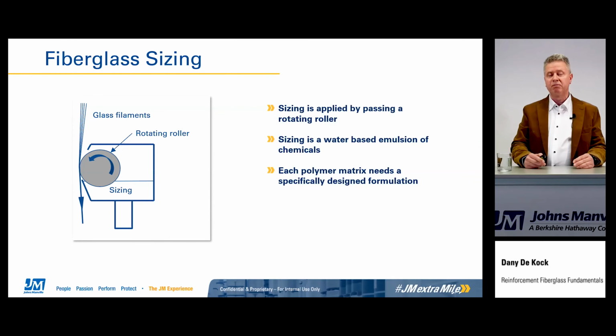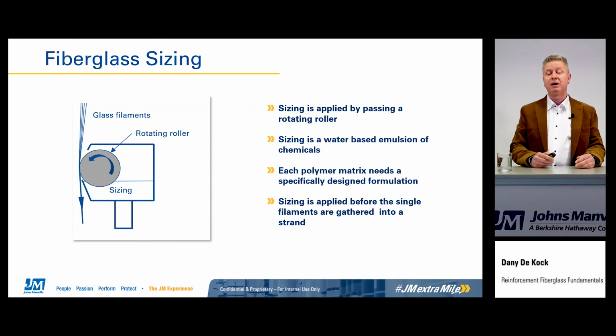And for each polymer matrix, if it's polypropylene, polyamide, unsaturated polyester, we need to have a special sizing. You cannot use a single sizing for all. You can try to have as many polymers covered, but then you give in on properties. So normally per polymer group or polymer type, you use a specific sizing. And we developed that sizing in-house. And it's a matter of long time trial and error, because it's not easy to develop a sizing in 6 months. It has to be trial and error in many cases. And sizing is applied before the single filaments are gathered into a strand. And you will see on the next slide how that is done.